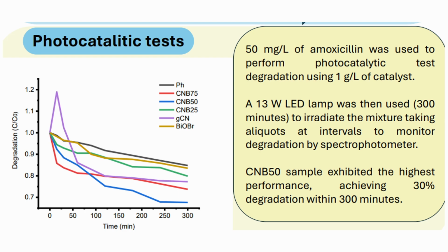To compare the enhancement of heterojunctions versus the pristine materials, we made photocatalytic tests of amoxicillin degradation. In this test, a 50 ppm amoxicillin solution is irradiated in the presence of the catalyst. This test was made with a 13 watt LED lamp. To monitor the degradation, aliquots of the reaction mixture were read with a UV-Vis spectrophotometer. This test showed that the CNB 50 sample, the 50% weight heterojunction, achieved 30% of degradation in 5 hours.